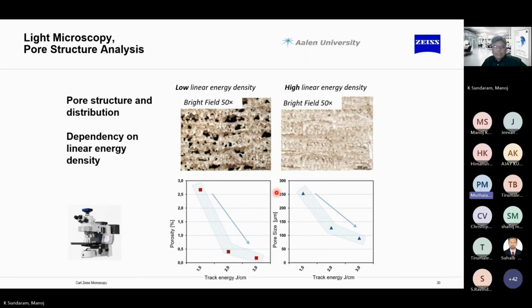Next slide. And with the help of image analysis software, we can also do the quantification of the pores and voids. Here we are trying to give you two different process parameters. On the left, you can see this is at 1.5 joules per centimeter in the printing process, where you can see a lot of voids are present. When you increase the track energy from 1.5 to 3, the voids are reduced to a larger extent.